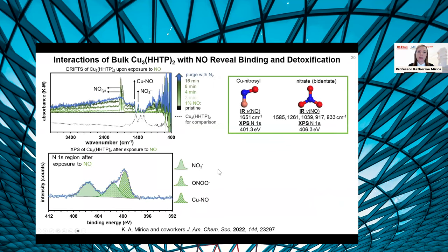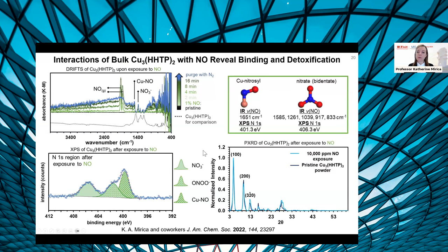In terms of interactions with nitric oxide, using diffuse reflectance infrared spectroscopy and X-ray photoelectron spectroscopy, what we conclude is that nitric oxide is actually getting oxidized on the surface of the framework, primarily to nitrate species upon binding, although we do also see some direct binding of NO to the copper centers within the framework. Importantly, the structure of the framework is maintained and the framework remains crystalline even upon exposure to 10,000 part per million concentration of nitric oxide.